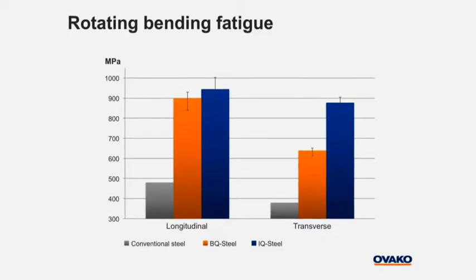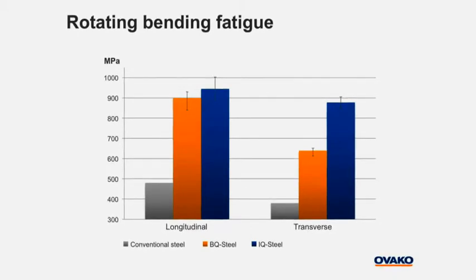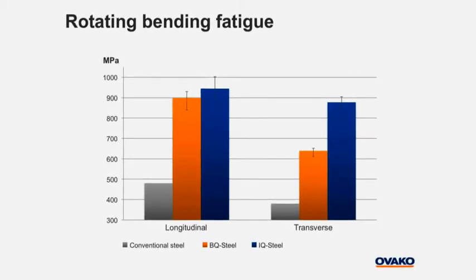Ovaco has conducted a huge number of fatigue tests with specimens sampled in both transverse and longitudinal directions. For IQ steel, there is a small difference, but not very dramatic compared to a non-IQ steel.